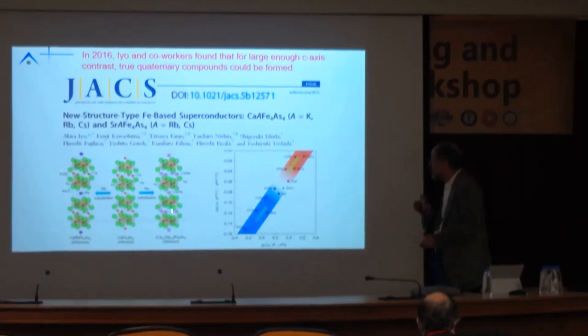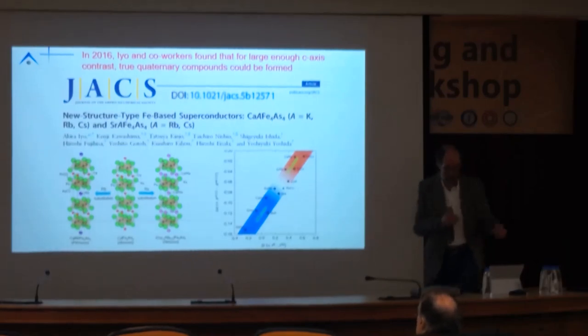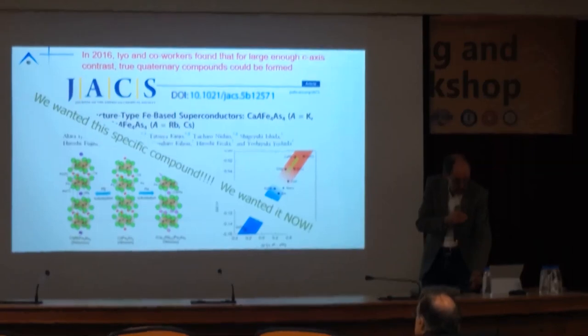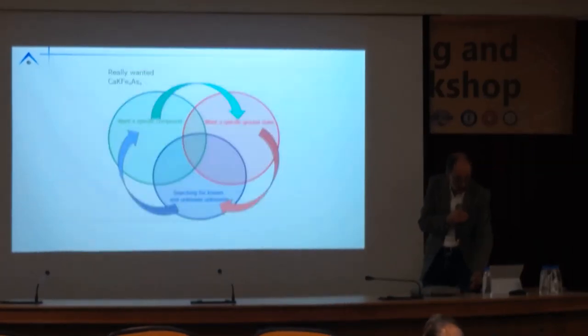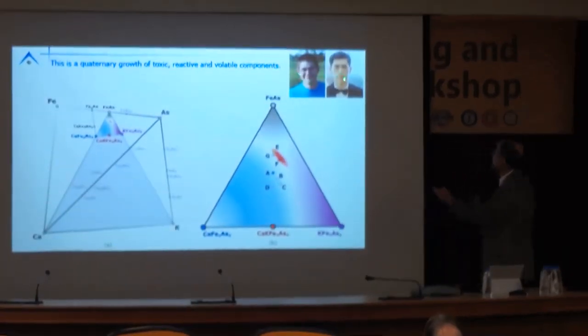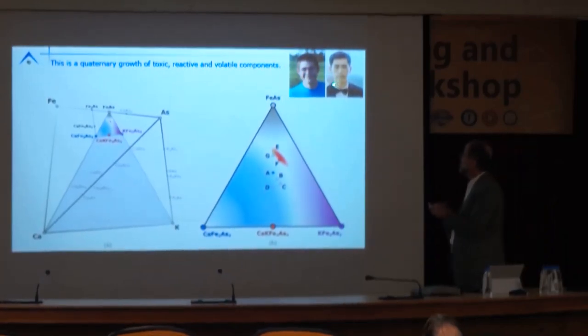On the other hand, if you have both c-axis contrast and non-epitaxy of the ab plane, you get a solid solution like the barium potassium iron arsenic that we all looked at. So, as a result of this discovery, we really wanted single crystals of this compound. So, we want a specific compound. So, William Meier and Tae Kong had a project to try to figure out, can we grow this? This is a true quaternary.